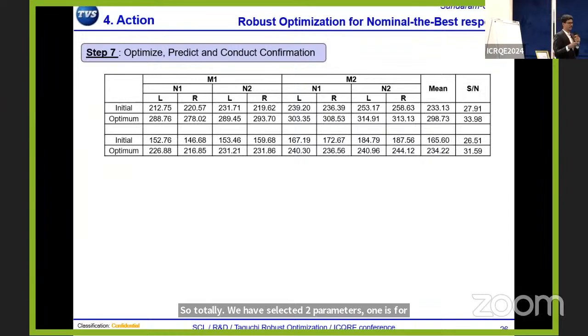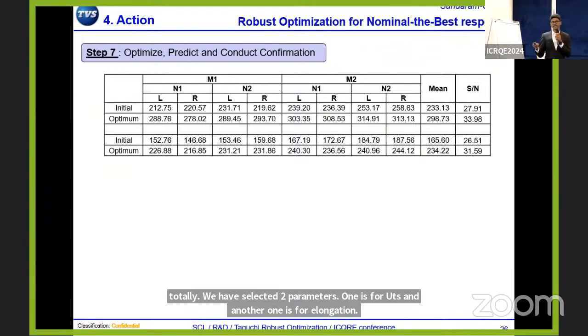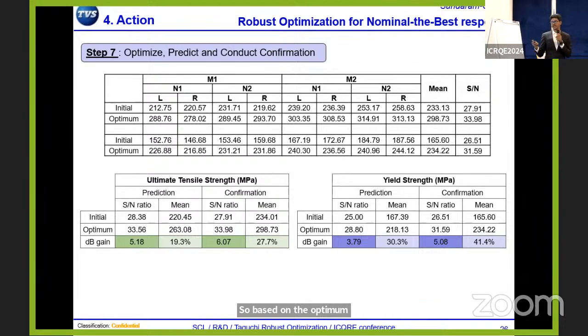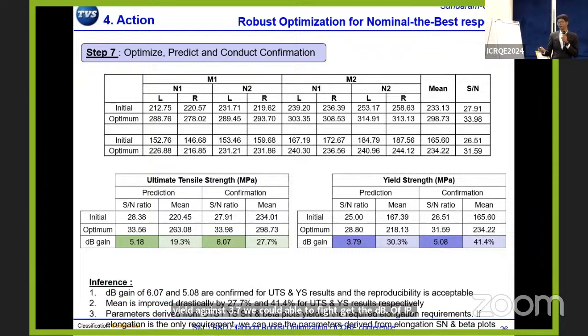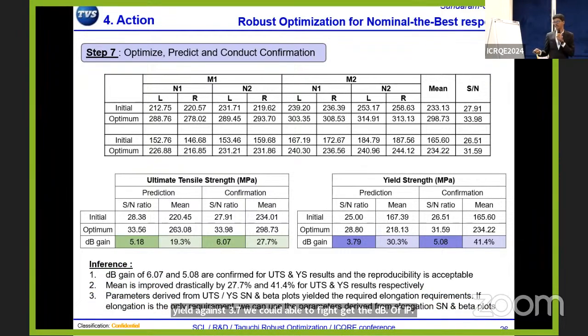So based on the optimum parameters, we have conducted the experiments, and prediction and confirmation are also done. Between prediction and confirmation, you could see that against 5 dB we could get 6 dB, and for yield strength, against 3.7 we could get 5.08 dB. So the reproducibility is acceptable. And also the mean is improved by 27%, and here you could see it is improved by 41%.